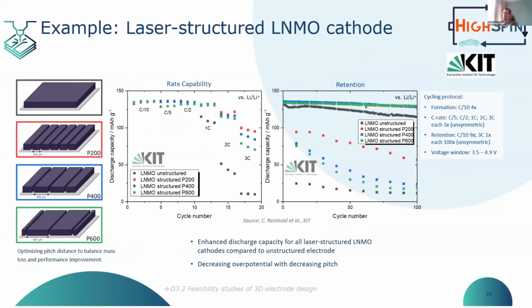Just to take one example here of the different kinds of patterns that we could envisage and some of the early performance that we've seen on the cathode side. If we consider, for example, a pattern with a pitch distance of 200 micrometers, you can see that at higher C rates, this particular electrode tended to outperform. If you look at the red dots, at increasing C rates, it had a better discharge capacity than unstructured electrodes or those with a higher pitch distance, so fewer grooves.